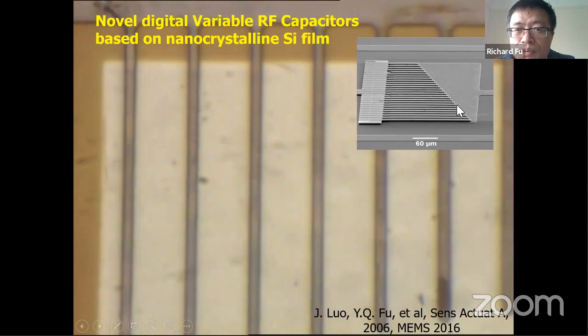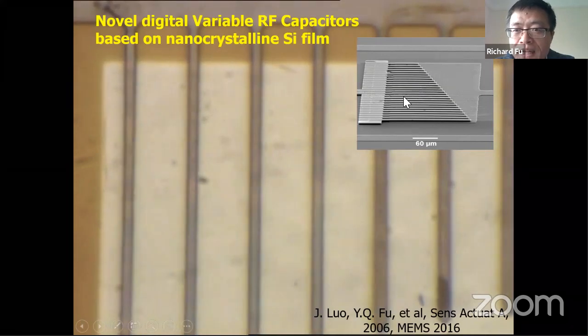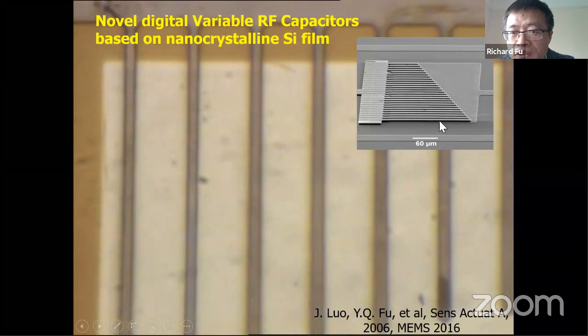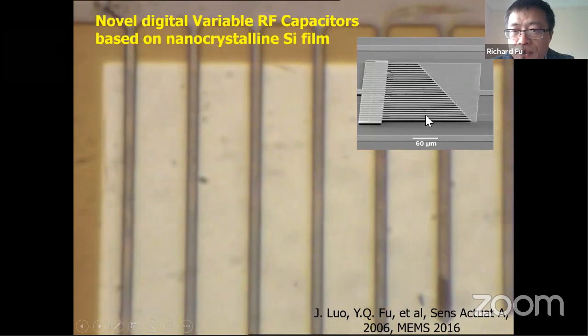And then we make a device with a two-layer structure. There is a top electrode, which is a multiple cantilever structure, separated from the bottom electrode, which is just a square-shaped electrode. So there is space between them. If we apply a voltage between the top multi-cantilever electrode and the square bottom electrode, there will be an electrostatic force between them, because the nanocrystalline silicon is conductive, doped with phosphorus, and the bottom is metal chromium or high-K materials. Because of the electrostatic force, the cantilever will be pulled in.